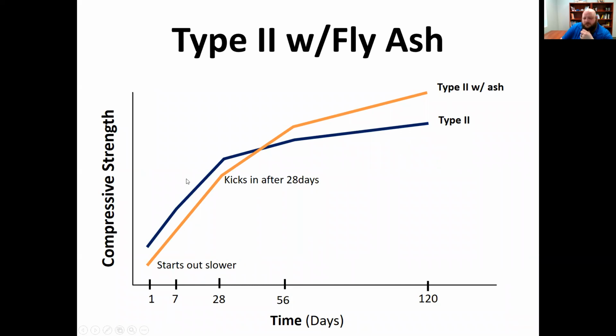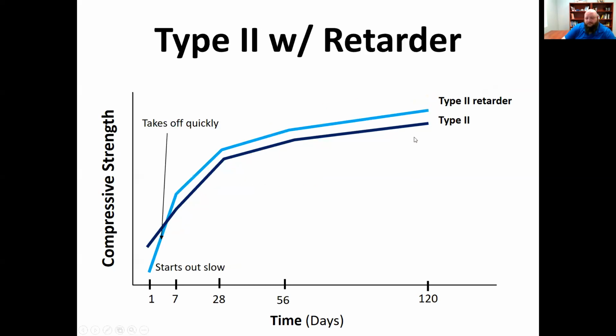So type 2 cement may look like this, the little baby blue line. And then you come in with an ash. It's important, you may have something that kind of starts off low, but maybe after 28 days, it may actually kick off a little bit, and it may even be stronger than the normal type 2 cement. So another thing is another type 2 cement, and you have a retarder that maybe you use at the very beginning. So it's going to start out super slow, but after a while, it's going to really take off.